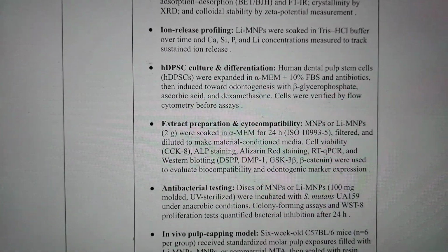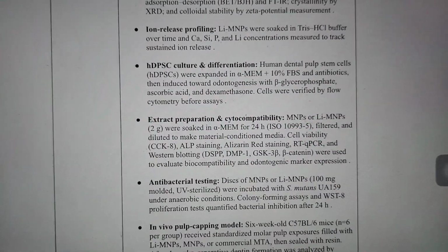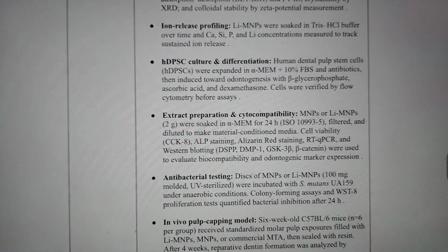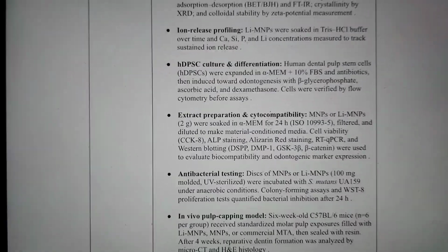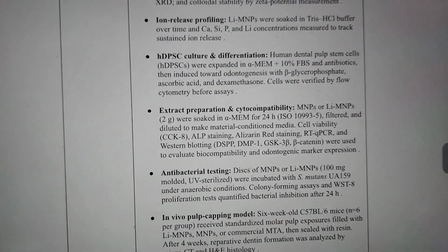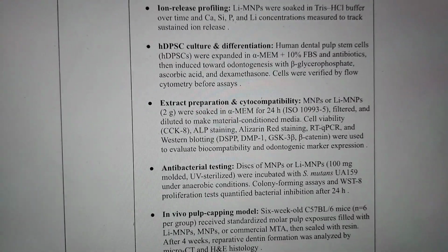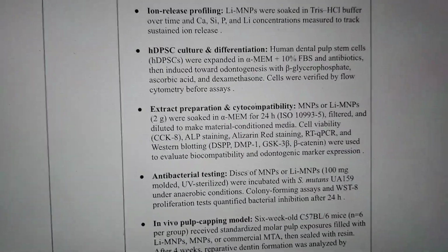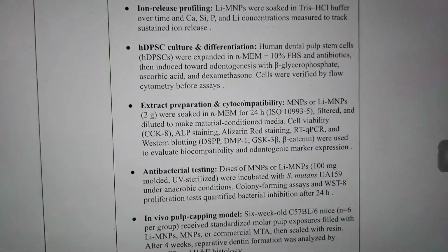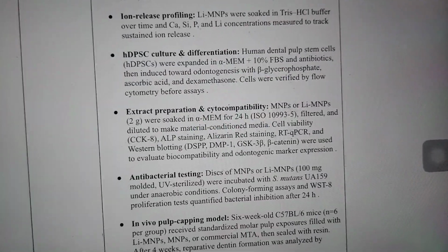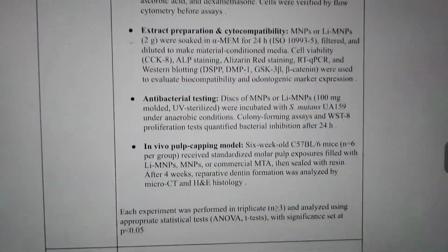Extract preparation and cytocompatibility. The developed nanoparticles were soaked in alpha MEM for 24 hours, filtered and diluted to make material conditioned media. Cell viability, ALP staining, alizarin red staining, RT-qPCR, and Western blotting were used to evaluate biocompatibility and odontogenic marker expression.